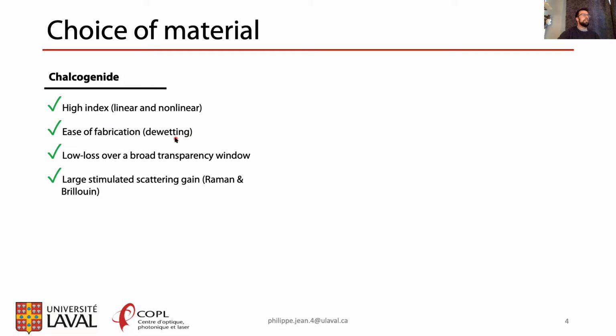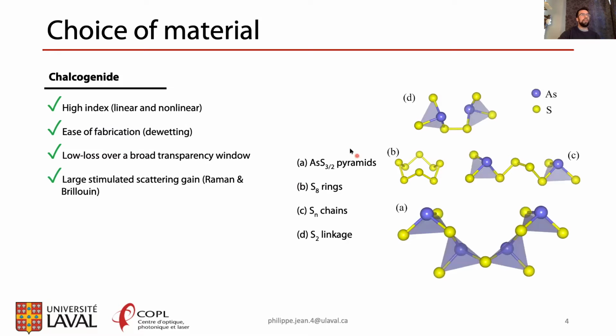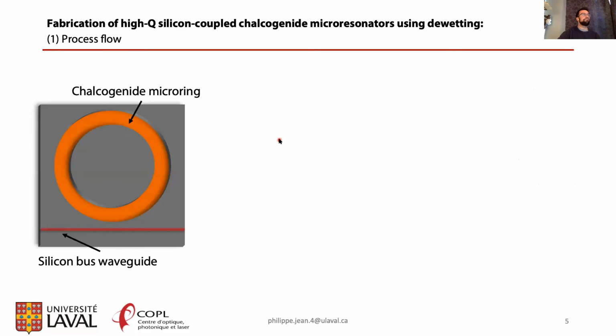Also, they're relatively easy to fabricate, at least for co-integration. They also present low loss over a relatively large transparency window that extends pretty far into the mid-infrared. And they also have very large stimulated scattering gain for either Raman lasing or Brillouin lasing. More specifically, the composition we chose to study is As20S80, and this is mainly motivated by the fabrication approach we chose to explore for the co-integration method.